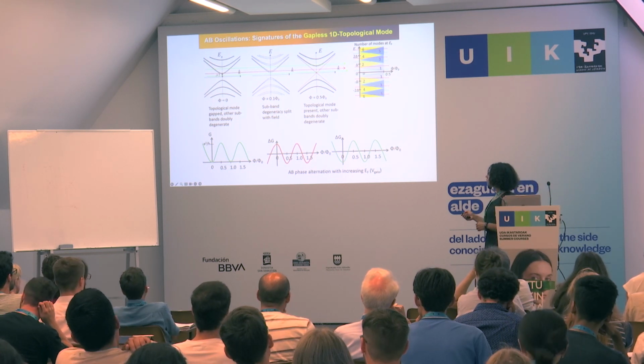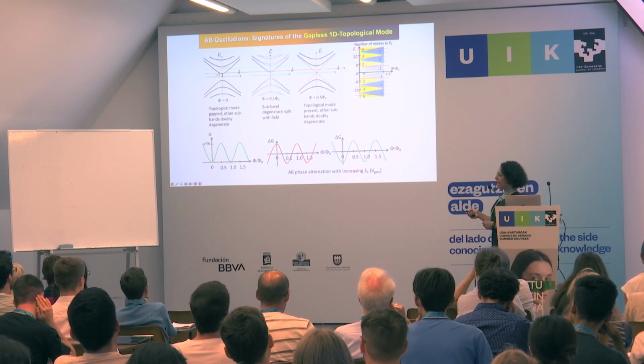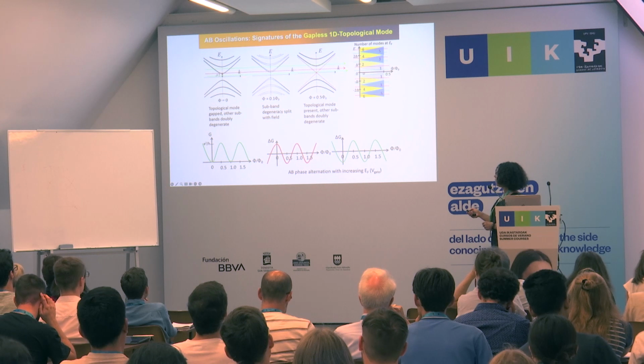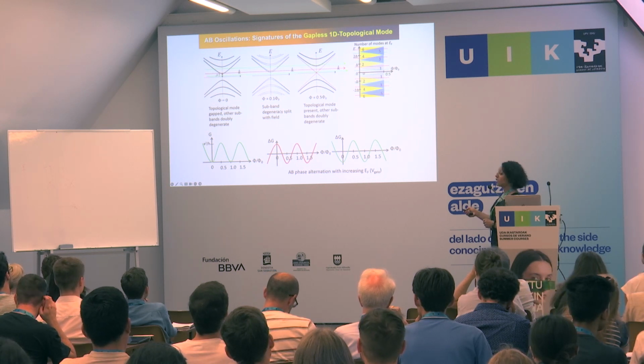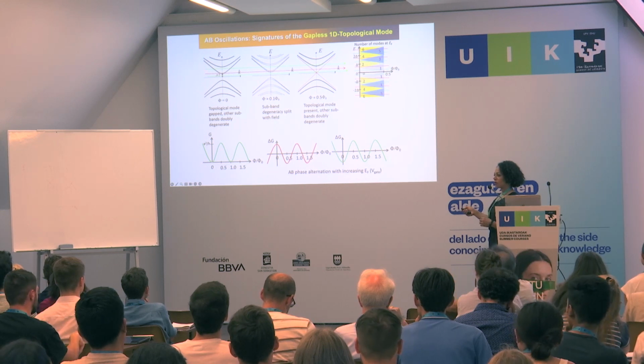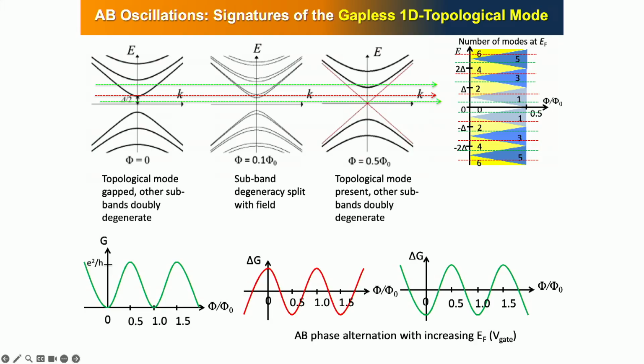So as a function of magnetic field, if you start with doubly degenerate bands that are gapped due to the additional phase at 0 flux, when we measure conductance, we're basically measuring as a function of gate voltage, right? So let's say we start at the Dirac point, and we have this green line going from the Dirac point, and we increase as a function of magnetic field. At the Dirac point, at 0 field, we should have 0 conductance, right? And then as we get to the Dirac point at half a flux quantum, we should have e squared over h, right? And then as we take this green one, here we should first have 2e squared over h conductance, because we have a doubly degenerate band there, right? And then it should go down to 1.